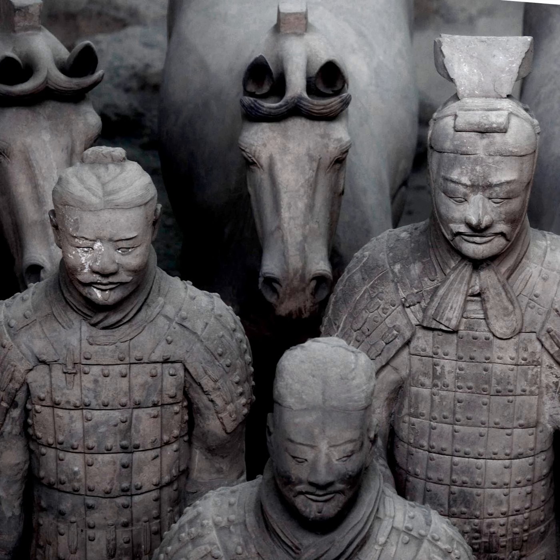Now, your final stage of smoking might include ramping the temperature up to just past the boiling point at around 120 degrees Celsius or 250 degrees Fahrenheit or thereabouts. This is to ensure that even deep inside the clay sculpture, every part is hot enough to boil out the water.